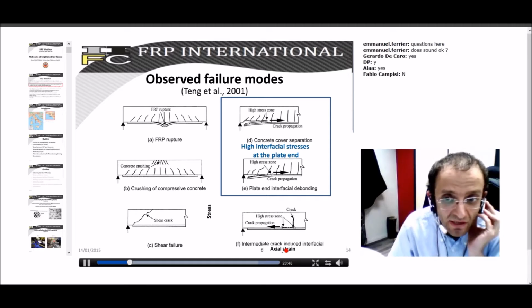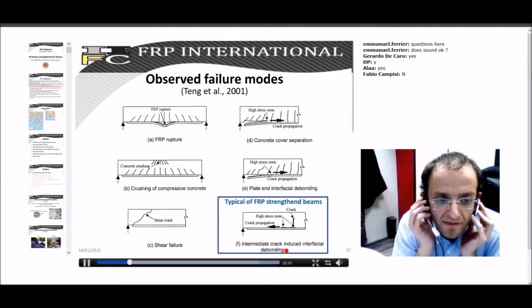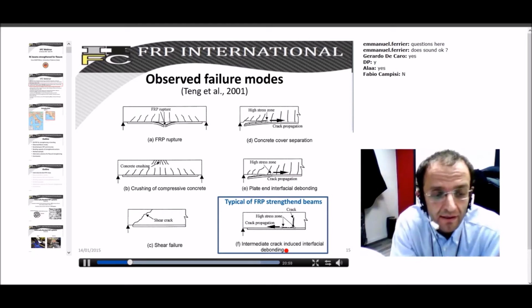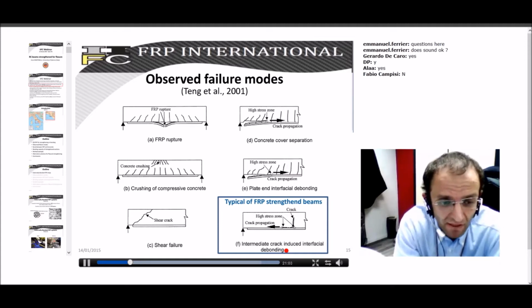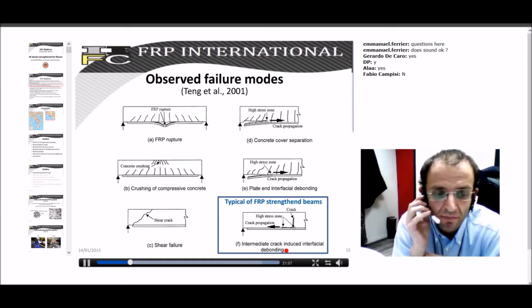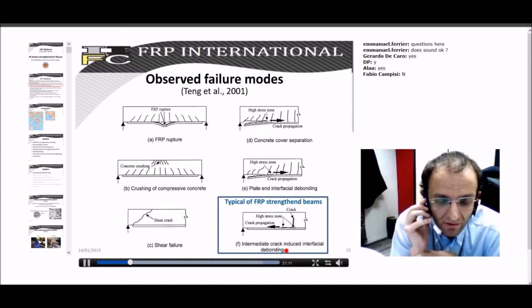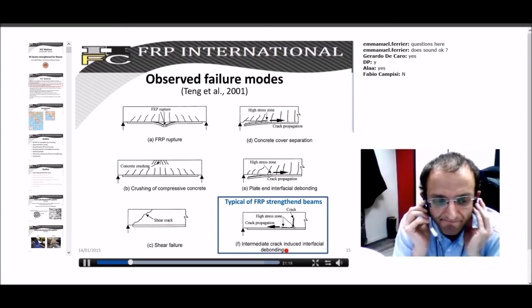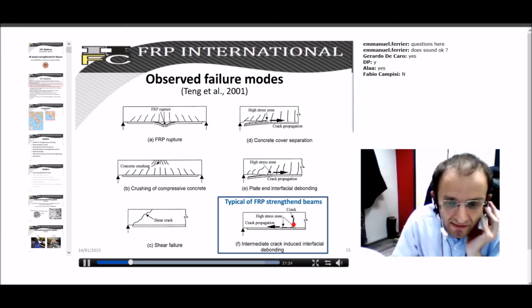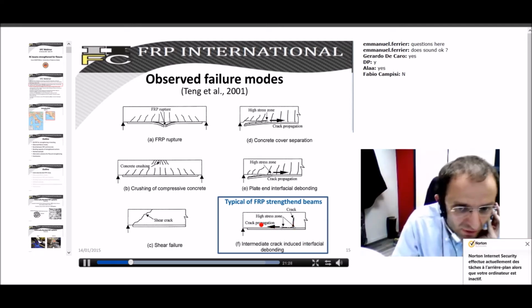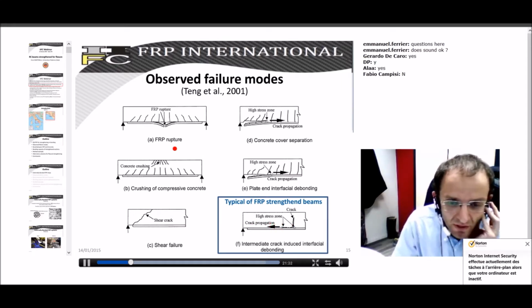And there is an even more typical failure mode, which is this intermediate crack-induced interfacial debonding, which is really a peculiar failure mode for FRP strengthened RC beams. And a significant part of my presentation will be devoted to giving a mechanical interpretation, a mechanical explanation of this failure mode, which is really a critical one. It is a failure mode beginning from internal cracks and then developing throughout the interface up to the end. So these are the new failure modes we have to face when we consider FRP strengthened RC beams. These are the new facts which we have to take into account.